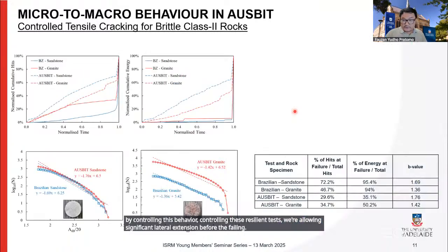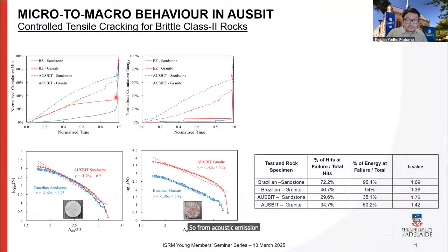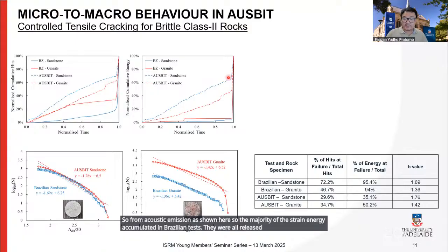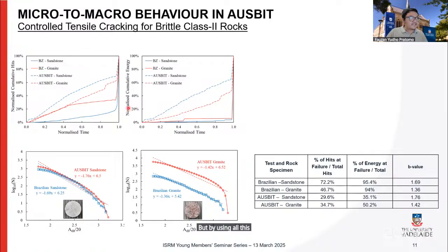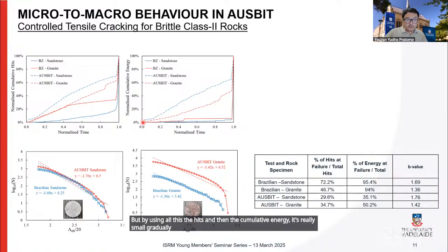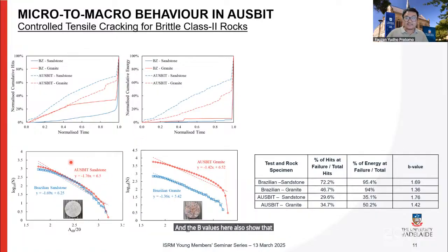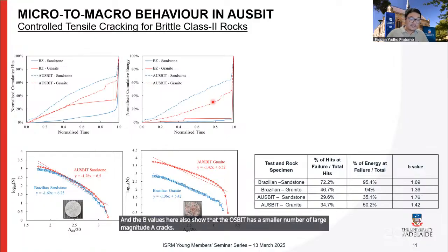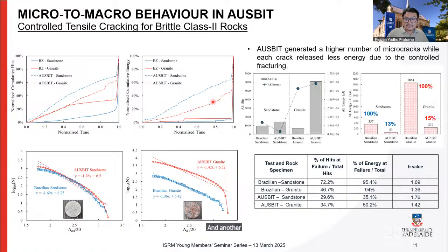From acoustic emission, as shown here, the majority of the strain energy accumulated in Brazilian tests was released instantaneously during the failure. But by using AUSBIT, the hits and the cumulative energy are released more gradually over time. And the b-values here also show that AUSBIT has a smaller number of large magnitude AE cracks.